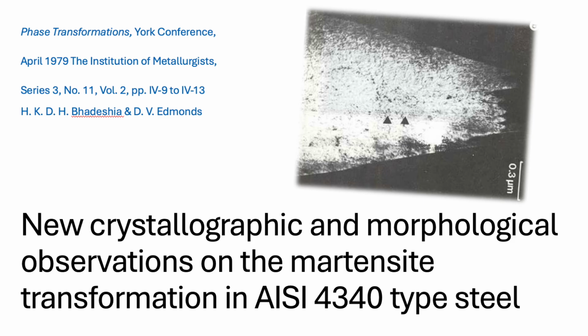Couldn't laths just form one after another and trap some austenite between them? You could think that, but the key is the stability of that film and what it implies about stress. If laths formed independently, the intense localized strain fields around each one would likely either force that austenite to transform or even cause microcracks. The fact that this thin, relatively weak austenite film remains stable between the laths suggests the stress is being managed cooperatively.